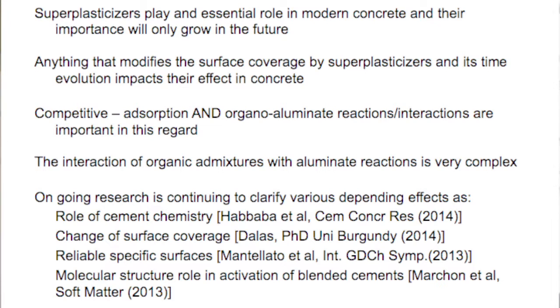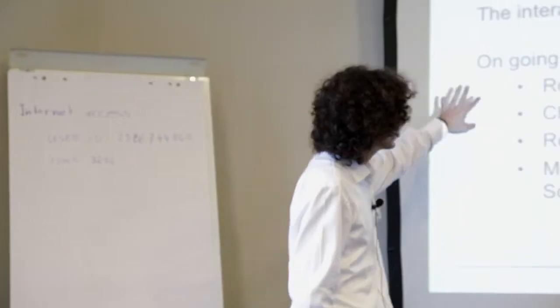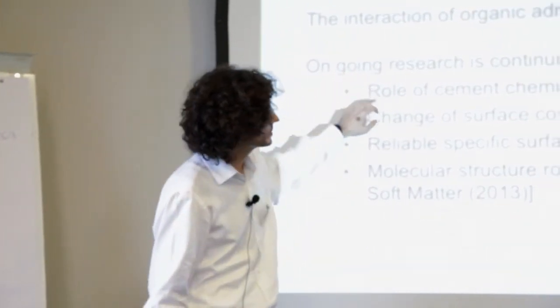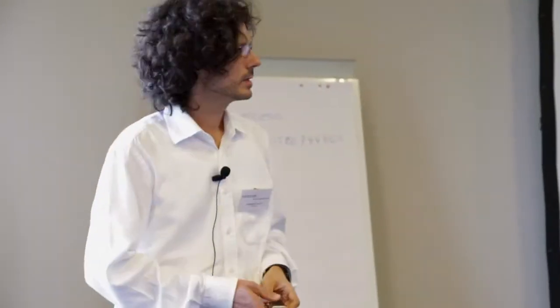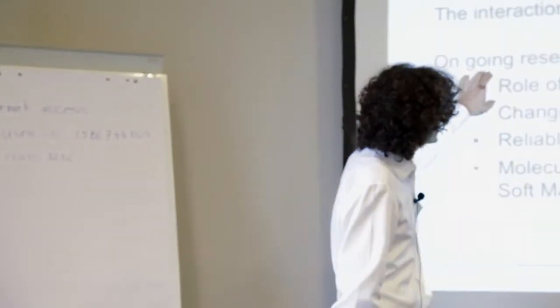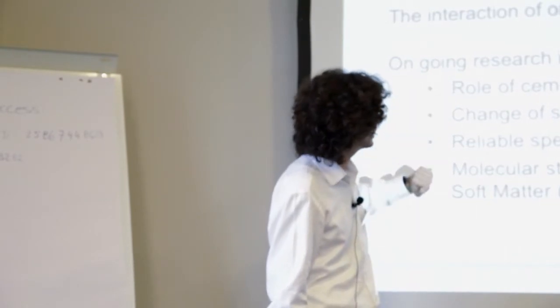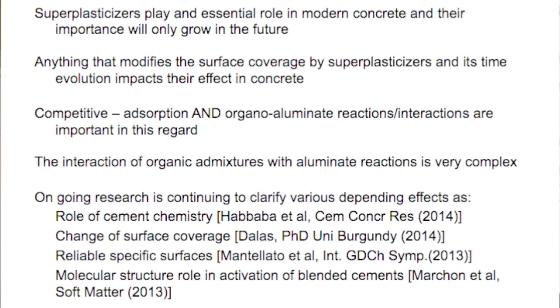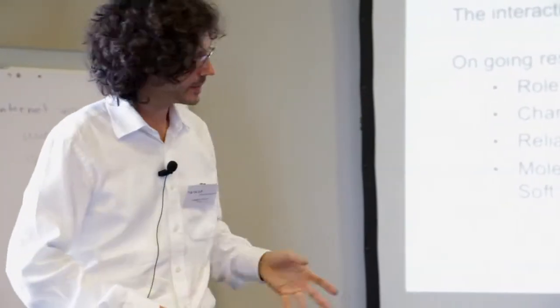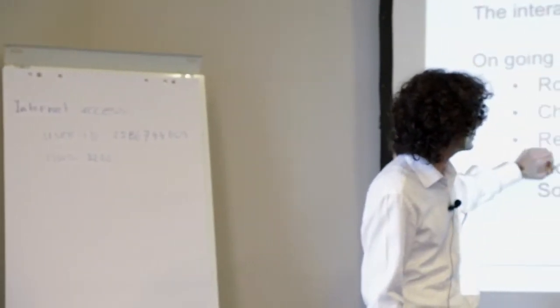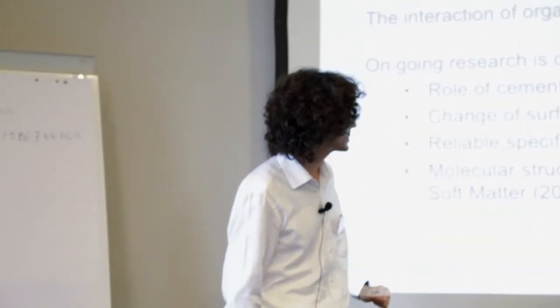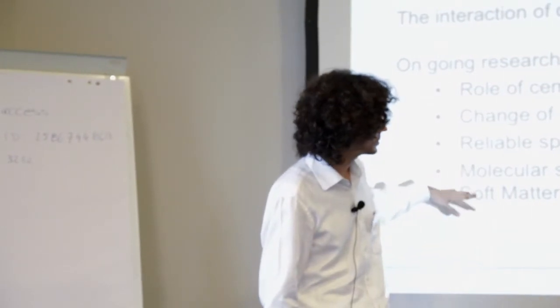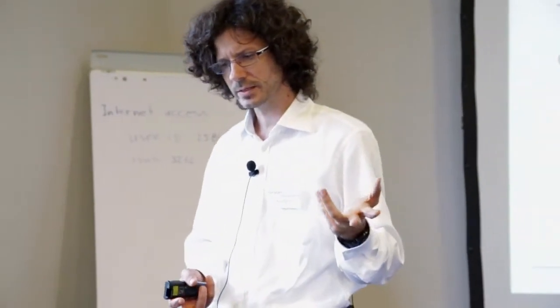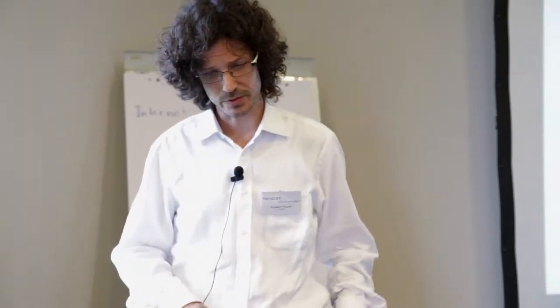I just would like to emphasize that this is an exciting subject. I think Nanocem has made a nice contribution to this field. And there's a number of ongoing research projects in different areas. I mentioned one at TU Munich with a recent publication trying to suggest how the chemical composition of a cement might or might not dictate the probability of formation or perturbation of rheology because of intercalation. The PhD thesis of Florent Dalas, recently defended at the University of Burgundy, looks at how surface changes caused or facilitated by the polymer modify in turn the rheology. We're working on similar areas, struggling with the notion of how to best determine the specific surface of these materials. And the equation I mentioned before was derived for understanding the competition between accelerators and superplasticizers, and that has also recently been published.